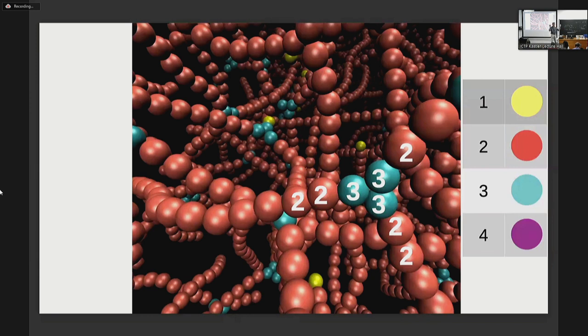And so with this model, tuned accordingly also to what we see in the experiments because it turns out that the scission, so the breaking of this living polymer is very costly at the level of kBT. 30 kBT is a lot, so it's not happening all the time, this kind of process. We can tune our parameter to meet these results, and I can skip the details of the model. And what we find in practice is that in a temperature quench, so we start with all the balls by themselves in the fluid, and then we lower the temperature suddenly so that they want to start to form the linear structures essentially. So it's a very strong quench. After some time, we start to see the formation of this network that resembles those of micelles.